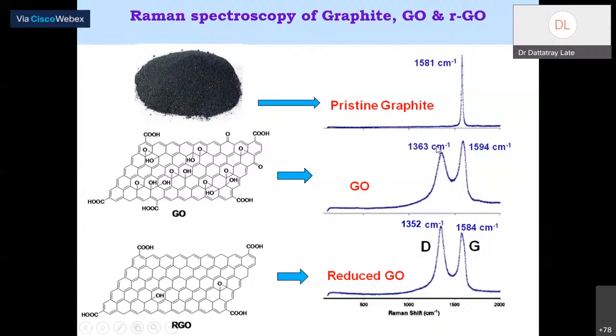Again, you can see the position of this particular G band. Now here 1594 centimeter inverse in this graphite oxide changes again to 1584 centimeter inverse in the reduced graphene oxide, right? And we see the D band is at almost a similar position. And you can see a very important change in the intensity of the D band and G band. Here in graphite oxide, the intensity of the G band is more, and in reduced graphene oxide, the intensity of the D band is more. Here, we actually introduce a large degree of defects in reduced graphene oxide. Therefore, the intensity of the D band is much more than in graphene oxide.